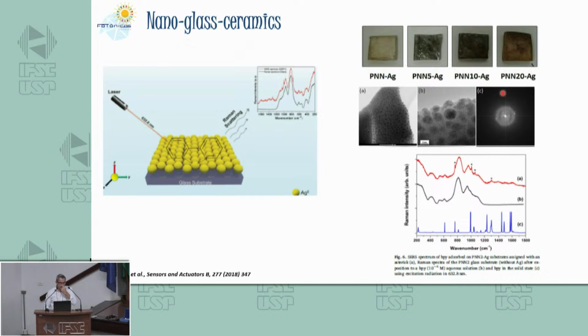So how do we use these properties of the nanoparticles? For example, if you have a glass, we can take advantage of heterogeneous crystallization. In this case, we prepare a glass doped with silver, and when we treat it thermally, the silver will move to the surface of the glass and crystallize on the surface. Okay? So for some molecules, we can use this effect for Raman amplification, for example. Many kinds of molecules have very small signals in Raman scattering.